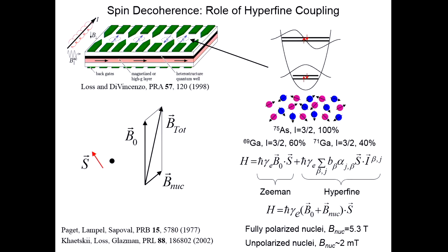But what happens is, due to this hyperfine interaction, an electron trapped in a quantum dot also sees a small field contribution from each nuclear spin that its wave function overlaps with. Okay? So you have an extended wave function, about 50 nanometers across, and it's overlapping with about 1 million lattice nuclei. And you can sum over all those lattice nuclei and calculate what the effective magnetic field is.